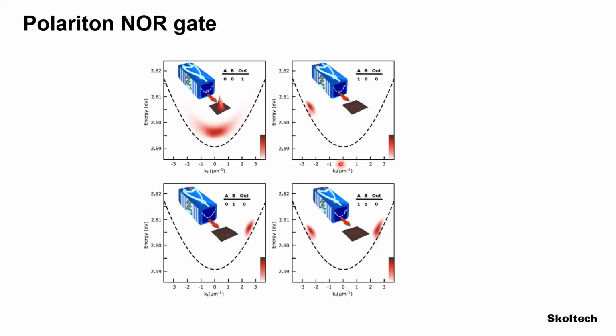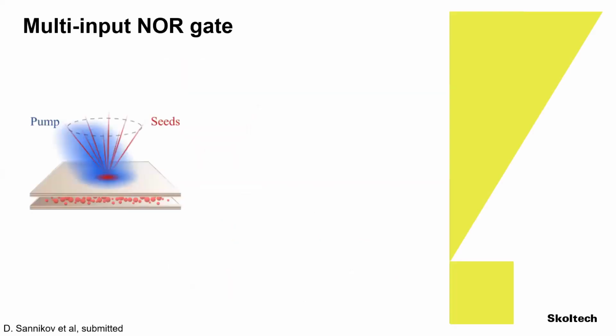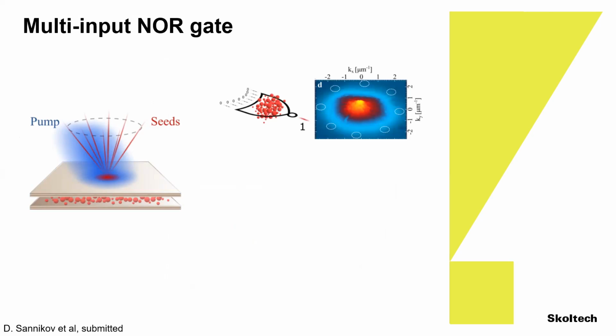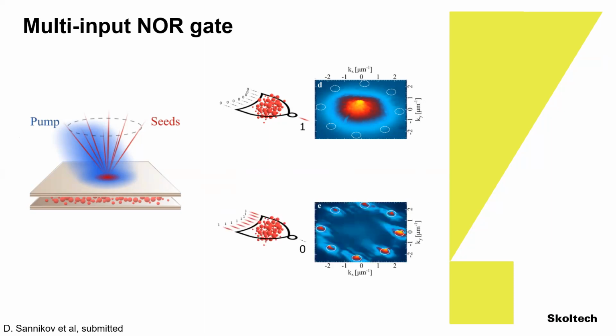And now, for the NOR gate, you need a few transistors in electronics. We can go yet one step further. We can use the fact that we don't just have a parabola, but we have a paraboloid. So now we can engineer our optical beam in reciprocal space and bring several seeds, so practically we control the angle of the control beam, and we can have several of them. This is now reciprocal space, kx, ky, so the in-plane momentum of polaritons in the plane of the cavity, and here is where I will be bringing not just two in opposite wave vectors, but several of them, 8 here of control beams. So in one gate, in one transistor, what we are showing here is that we can have 8 inputs. So we can create an 8-input NOR gate on a single transistor. That gives you a compression of the scalability of 64 at least, if you look at it from a logic gate electronic transistor perspective.